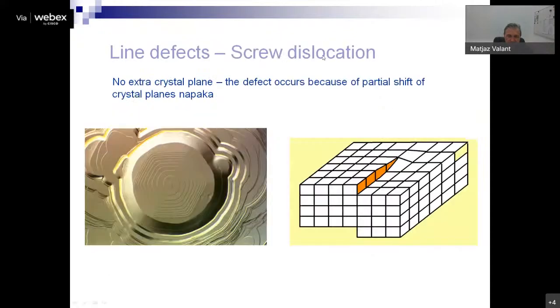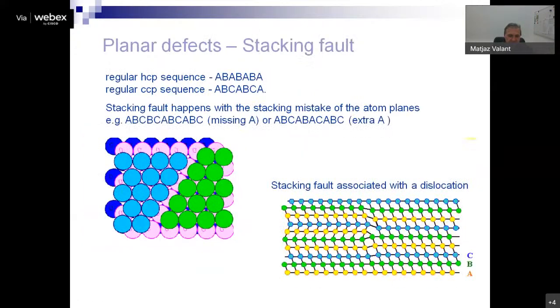Another is a screw dislocation. We don't talk about any extra plane here, but we just talk about the shift of the planes, like it's shown here. And then when the crystal grows, it grows around this dislocation, around this dislocation. It is shown here in such a spiral way. So silicon carbide is a typical representative with a lot of screw dislocations.